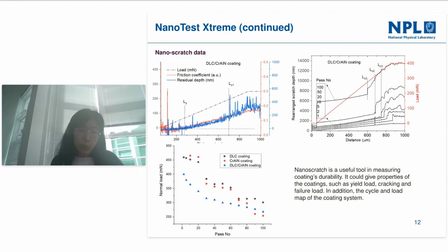Here is an example of both single and multiple pass scratch tests on a composite coating on a tool steel substrate. And for instance, on the top left images, from this you can get the yield load and also the load when the radial and the lateral cracks develop as a function of ramping load.